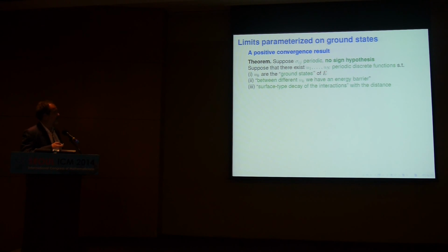So you can formalize this. Suppose that you have a finite number of ground states. These are periodic functions, which are minimizers. I don't give the precise definition because it's complicated. And between two of them, there is a positive energy barrier. So you can't go from one to the other, staying at the minimum. And then you have to assume, of course, some surface type decay. Otherwise, you can't obtain a surface energy.